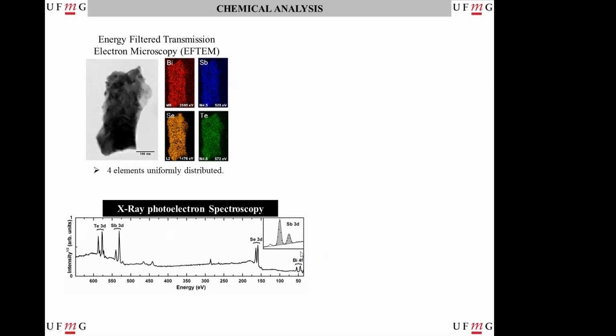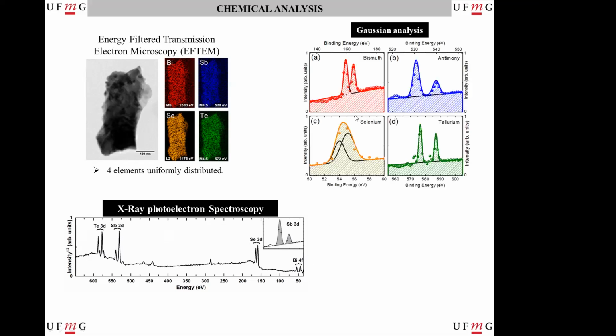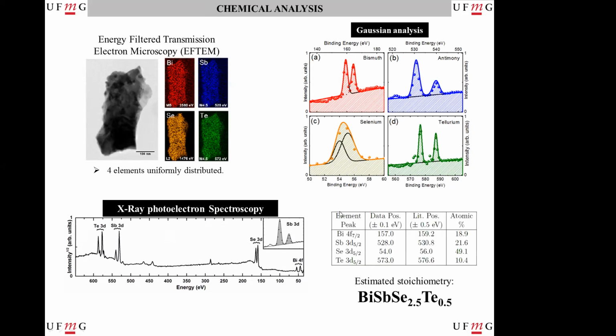of our sample here. And for each peak, we try to analyze it using a Gaussian analysis. We can fit a Gaussian on each peak, and we try to estimate the amount of each element in our sample. Using this analysis, we can retrieve the estimated stoichiometry of bismuth 1, antimony 1, selenium 2.5, tellurium 0.5.